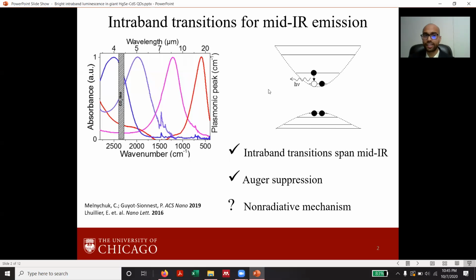Mid-infrared detection using interband transitions in narrow gap semiconductors is a well-established technology. In comparison, detection using intraband transitions have several advantages. The intraband transitions span the entire infrared range from the long wave to the short wave, like we see in this tuning curve for mercury selenide quantum dots. Due to the sparse density of states of the holes, we see suppression of Auger relaxation.